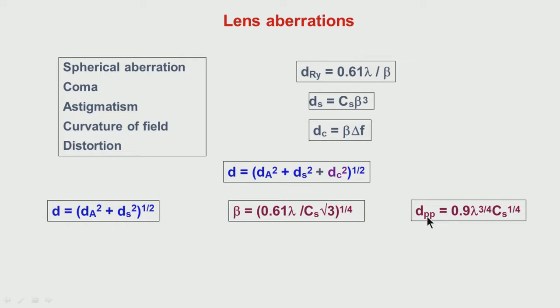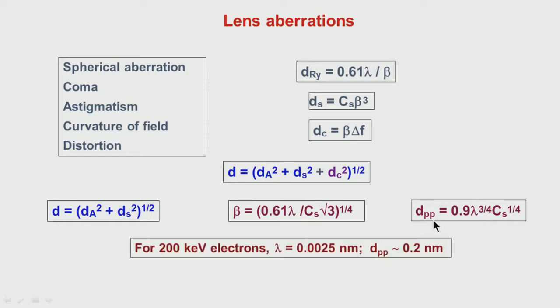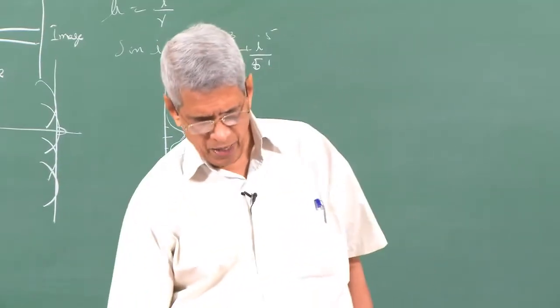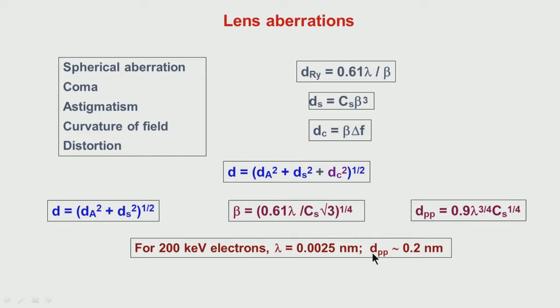And we can also find out from one point to another point in that object, what separation we can measure. This is lambda to the power of 3 by 4 and Cs to the power of 1 by 4. That means that small variations in lambda can bring about a lot of variation in the resolution. Okay. And in fact, here I am just showing the value which has been calculated for 200 kV electrons, where lambda is of the order of 0.0025 nanometer. Then the point to point resolution which we can obtain for the image of the object turns out to be 0.2 nanometers. So it is 100 times worse than what the Rayleigh criterion dictates.